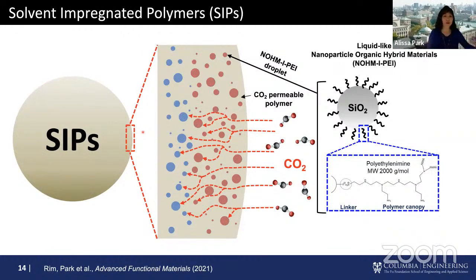This system is very simple to make. So what we do is start with the UV cured polymer, and then we put our NOHM material, which is viscous, mix them together, but use high shear to make sure that we made an emulsified system. By doing so, we can make sub-micron droplets, and then you can cast them into a flat surface and UV cure, and you can make different shapes and sizes of particles by grinding them.